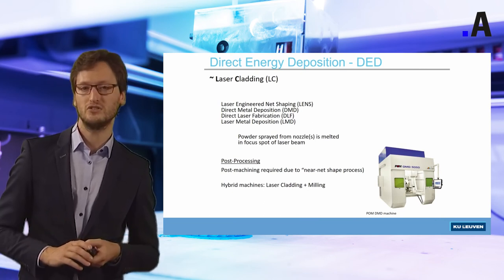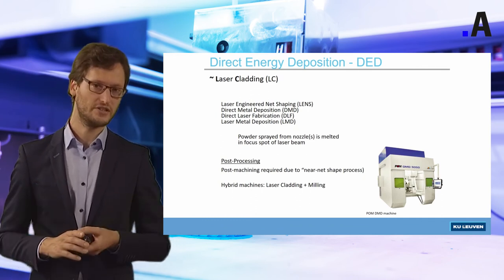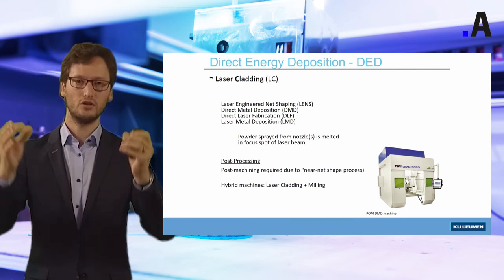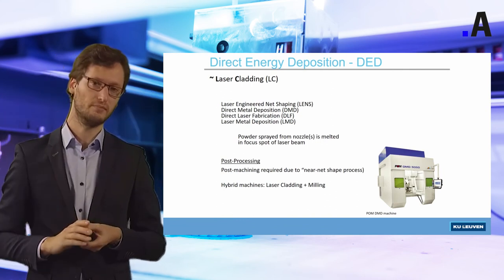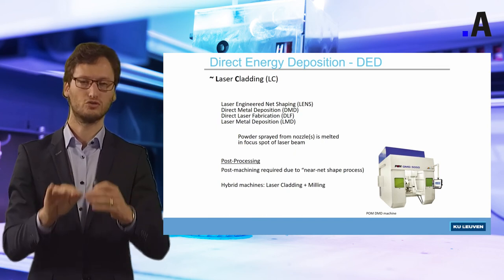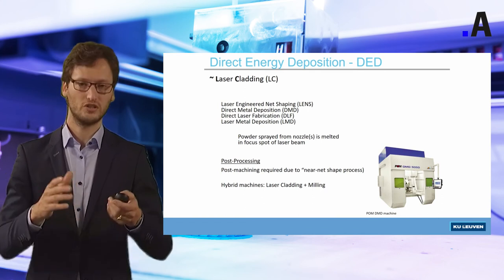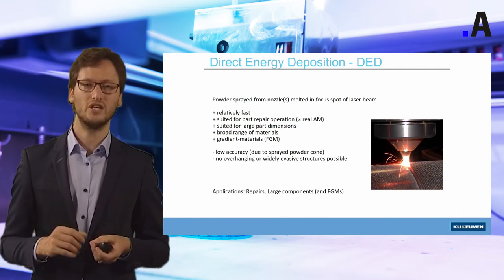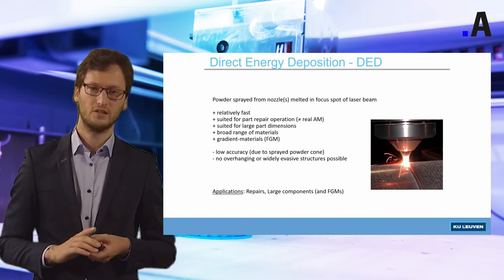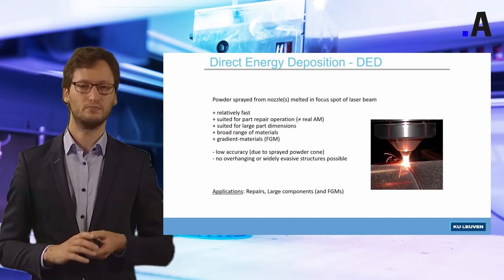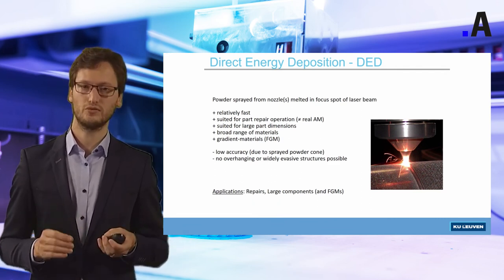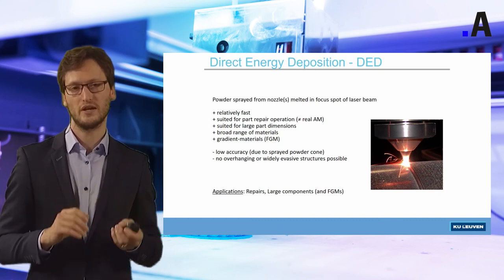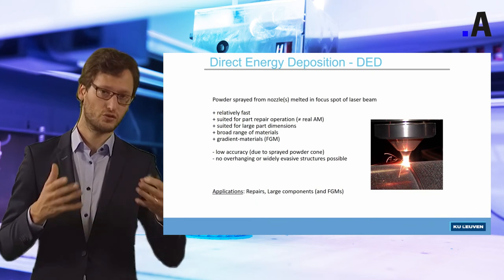The last technique for printing metals is direct energy deposition, or DED, also called laser cladding. In this technology we do not start from a powder bed but use a nozzle. In the nozzle there is a flow of powder particles and a laser beam in the middle. The laser beam melts the powder particles on top of an existing part or base plate. Basically, powder is sprayed through a nozzle and melted in the focal point of a laser going through the same nozzle. This technology is quite fast and can be used to process very large parts. It can also be used for repair — for instance, if a large part has a small crack that can be machined away, that hole can be filled again using DED, which is economically interesting.